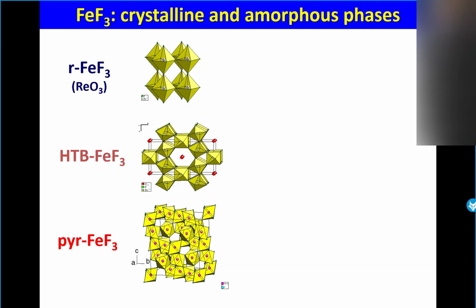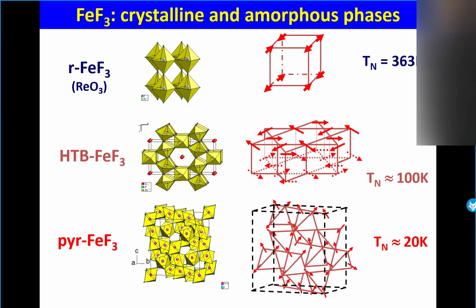So as you can see, this FeF3 is very nice because you have the same chemical composition, but you have 3 different crystalline phases. The rhombohedral one, the HTB one, and the pyrochlore. Okay? So if you look carefully at the magnetic structure, you can see the first one is a typical antiferromagnet. You can see also the Néel temperature, 363 Kelvin. Then you have the HTB, and you can see a decrease of the Néel temperature.